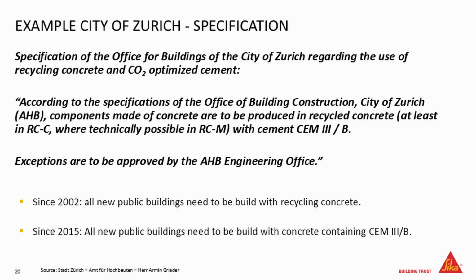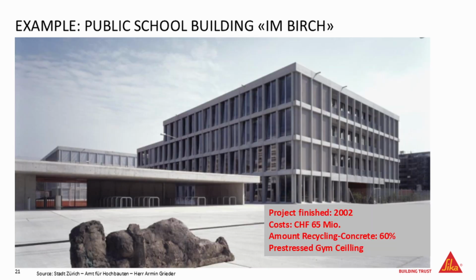And that resulted in some pre-tests done with contractors and with recyclers, because you need to make sure that you have enough material available when you specify this. It needs to be available. So some recyclers around Zurich needed to be in the boat, and the contractors and the ready-mix producer to produce a certain quality of that material. But the decision was done very quickly, because it was already in 2002, and a short time later the first buildings were produced. For example, this is a public school building in Birch.